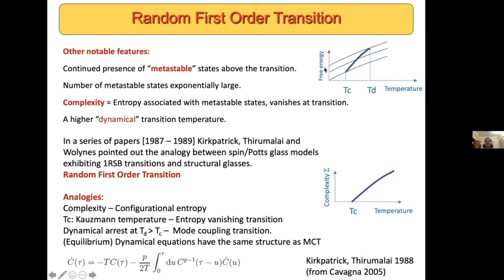This is sort of schematically shown here, where on the y-axis, I have free energy of individual states. And on the x-axis is the temperature. So the thick solid line that goes across is the total free energy of the full equilibrium system. And the first point I want to point out is that these individual states continue to exist beyond Tc, which is the transition, which I'll describe in a minute. And the second notable feature is that these metastable states are exponentially large in number. So one can actually define an entropy associated with these metastable states called the complexity.